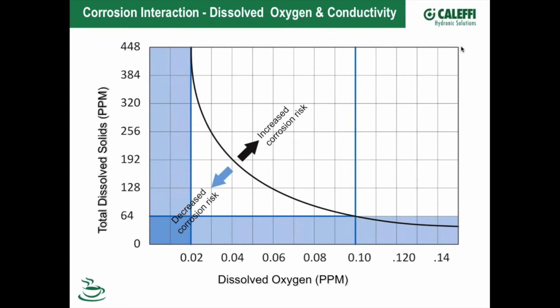And through the repeated cycles of water going through the process, getting boiled, coming out, or it could be even a heat pump, quite frankly, you do scrub the water, and your dissolved oxygen starts to migrate down. Now, even at that, until you heat the water substantially, the dissolved oxygen content is probably going to be north of 0.10, as you see in the chart here, all right?